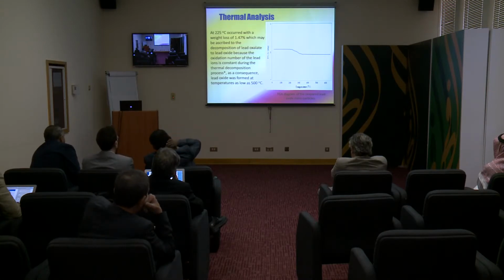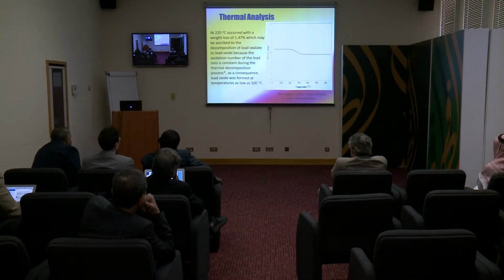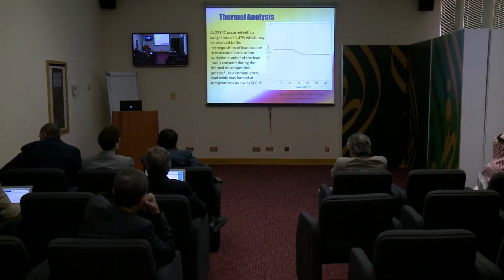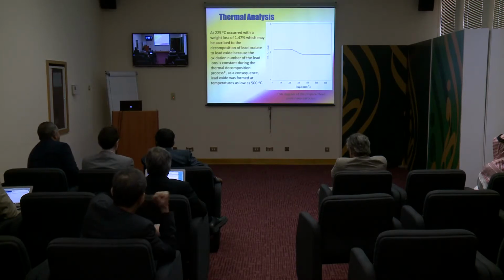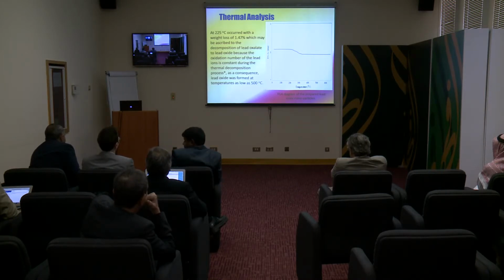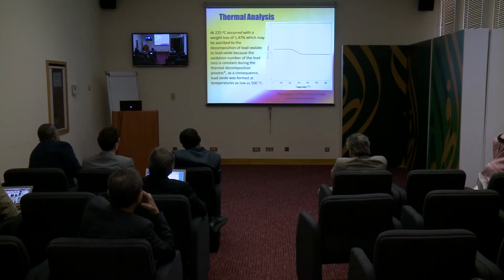Thermal analysis, also by thermal gravimetrical analysis at 225 degrees centigrade, occurred with weight loss of about 1.47 percentage, which may be ascribed to the decomposition of lead oxalate to lead oxide because the oxidation number of lead ions is constant during the thermal decomposition process. Lead oxide was formed at temperature as low as 500 degrees centigrade.